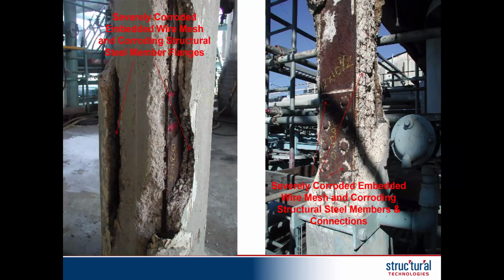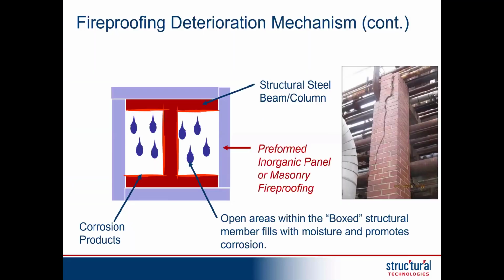Now, we do see some of these inorganic panels and even masonry that's used as fireproofing. Unfortunately, what we see with these kind of boxed out regions is that the areas within these boxes that are sealed, essentially the humidity will go to 100%, because when we open them up, we see condensation on all the surfaces. We see significant rust. The photo to the right is showing a masonry column that originally had a steel column in it. This had been built in the 1930s for a very old refinery in the U.S., and we found that the steel column actually had no base to it anymore because it had totally corroded, and literally the masonry was holding up the pipe rack. So it was very serious, and we immediately had to shore those regions based on our inspection and some of the inspection excavations we did.